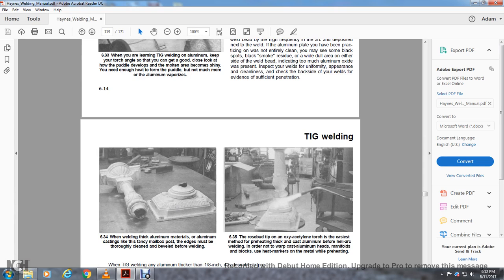When welding thick aluminum material, such as aluminum castings, the weld edge must be thoroughly cleaned and beveled before welding. The rosebud tip of the oxyacetylene torch is one method of preheating thick cast aluminum before the heliarc welding. In order not to warp cast aluminum heads, manifolds and blocks, use heat markers on the metal while preheating.